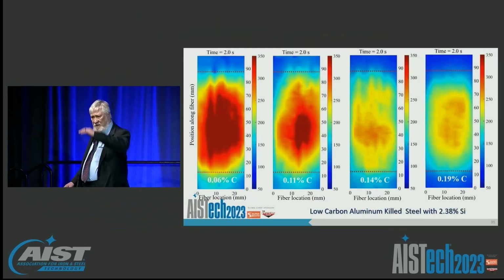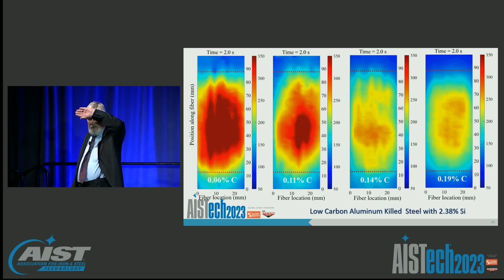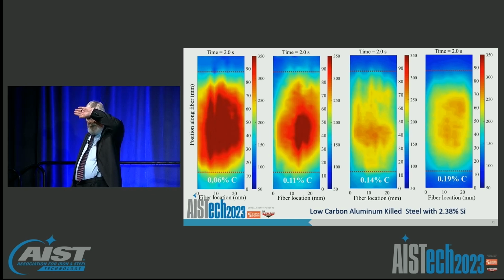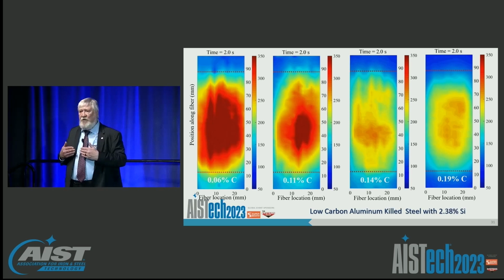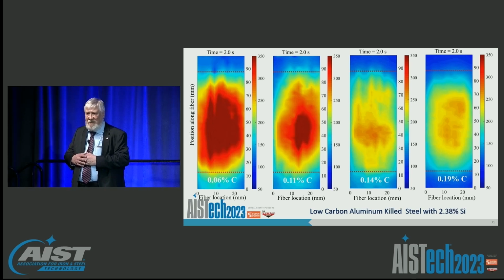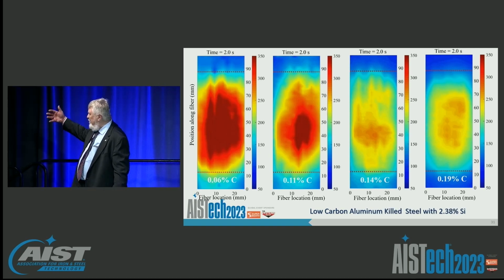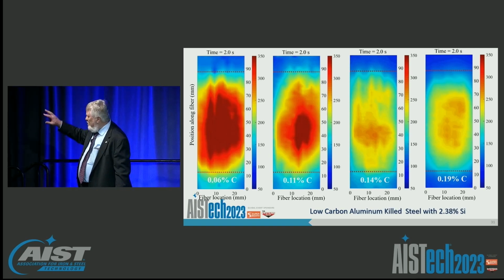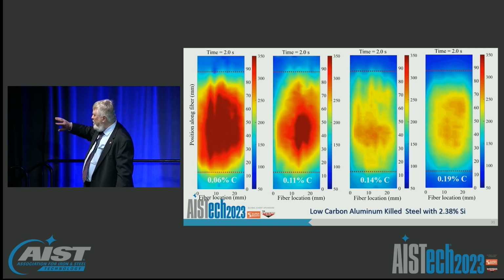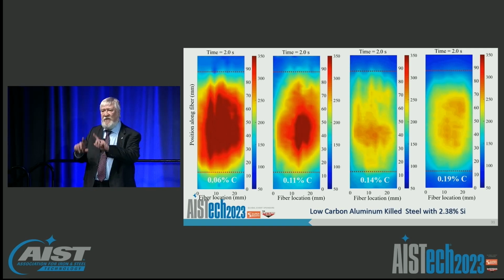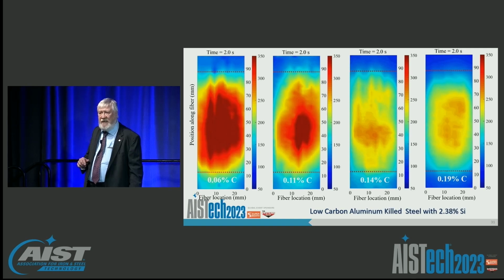Because the impression I got out of it is that the thing that is special for peritectic steel grades, it looks like it's not so uniform. Yeah. Well, there are two things in the peritectic. One is non-uniformity and pull away, right? Yes. And we can see the effect on heat extraction here. Right now, we're not seeing a lot of the details, and it's probably because of the size of our test that you're not seeing all the shrinkage details.